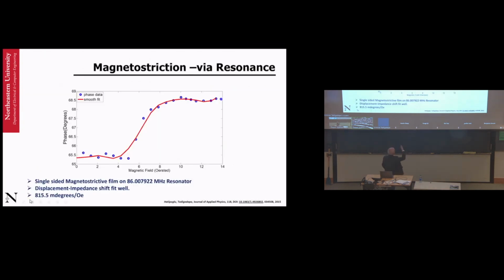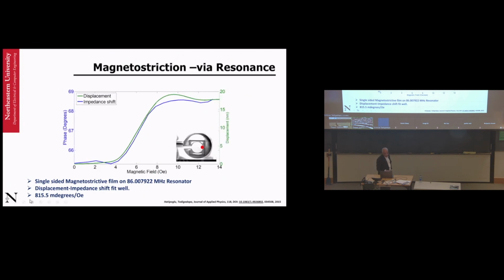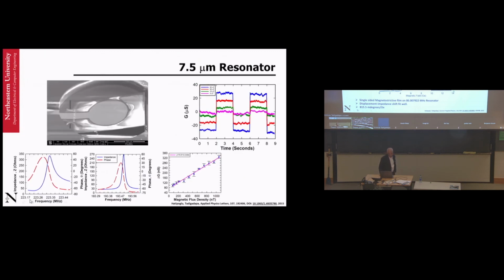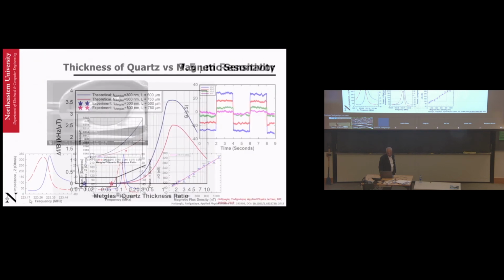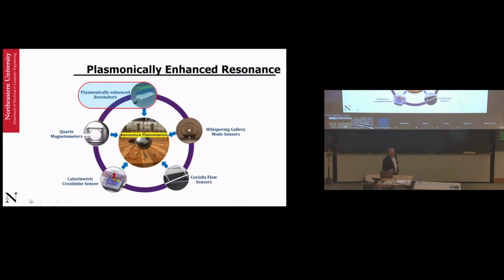So here is a result, for example, of the measurement of the resonance frequency as a function of magnetic field. And here is the same measurement with a laser vibrometer, where we are looking at the out of plane bending of this. So again, proof that the device is working the way we intend. So again, I will not probably go through all of this, but you can see these as we are bending them out of plane. And there is optimization that you can do.